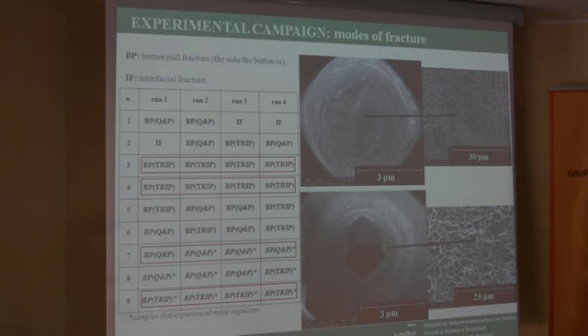In particular, you can see that in this test, in this other test, the fracture was characterized by the button pullout occurring on the TRIP side, and then we can consider that in this case we have all the fractures occurring in quenching and partitioning steel. At the moment it is not clear if there is a correlation between the side of the button pullout and the test.